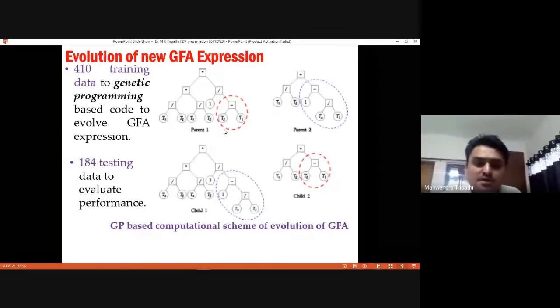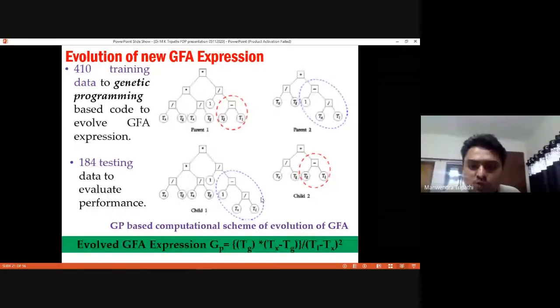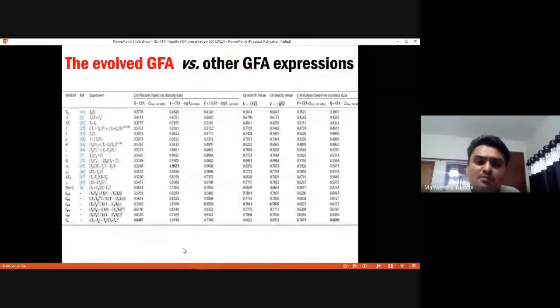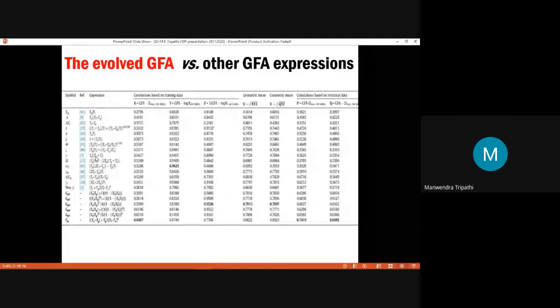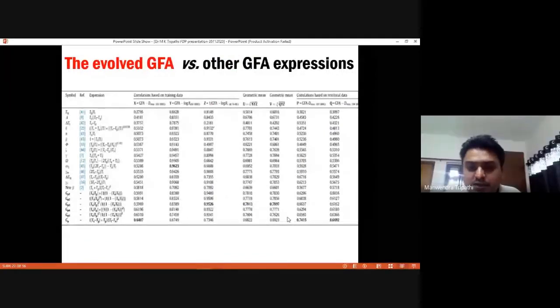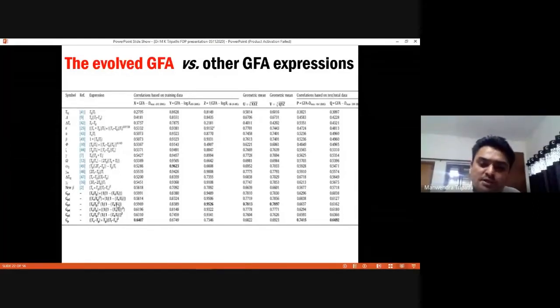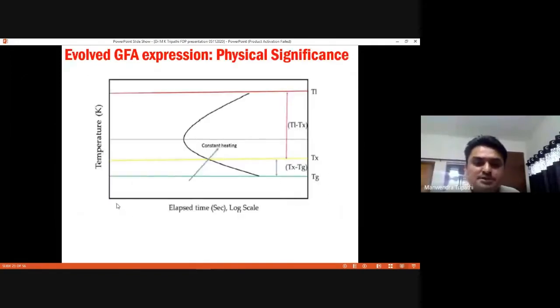And after doing it, it is giving us this correlation, which we have finally decided should be taken as the new GFA expression. So now we are comparing our expression, which is kept over here, with the other published expressions in terms of TG, TX, TL. We find that the correlations are significantly higher. We have compared on various bases. I'm not going to explain those bases, but we find that these correlations are significantly higher than all proposed correlations. So this is one example where the data-driven techniques are useful to solve such physical problems.